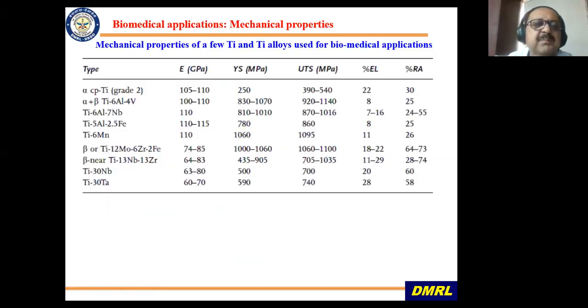Here again, I'm showing the properties of different alloys used for biomedical applications and their modulus, strength levels, elongation, etc. And you can see these newer beta alloys have much lower modulus as compared to alpha plus beta or alpha alloys. And the strength is actually not a criterion, but you have to have sufficient strength, that is all. But strength has never been a criterion for biomedical application. So people are designing new alloys for biomedical applications.